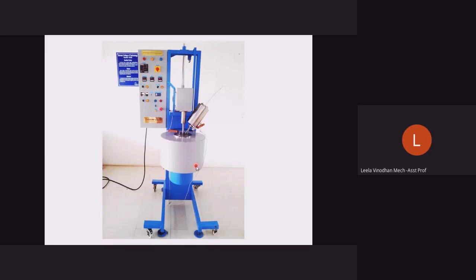So this setup, what is shown here, is basically for the aluminum. It's an aluminum stir casting furnace. So magnesium stir casting and aluminum can be done in the same setup. But the problem is we need to have additional setups, like the cylinders, argon cylinder and SF6 cylinder, and then provision for controlling the gas flow and how well we are going to maintain the gas flow. There are even research articles in which they have changed the mass flow rate of the gas and then checked the casting. So there are certain variations in the results. So you can try in that aspect also.